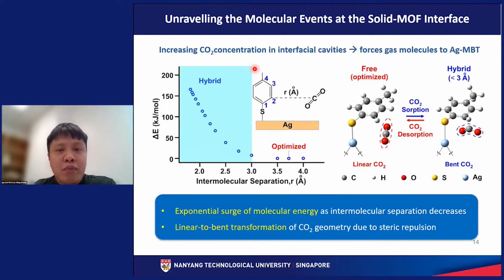Next, we want to unravel the molecular events at the solid MOF interface. In this case, we use DFT, or density functional theory, to simulate what is exactly happening to our cells as well as to our molecules. Before we do this, we have one hypothesis: if we flow more CO2 into our system, there will be an increasing carbon dioxide concentration in the interfacial cavities, and this will ultimately force gas molecules towards our silver MBT surface.